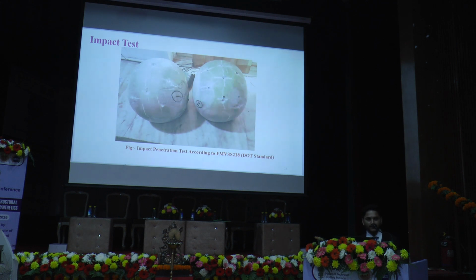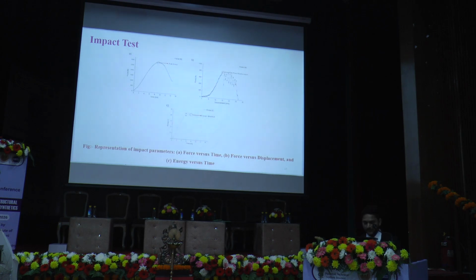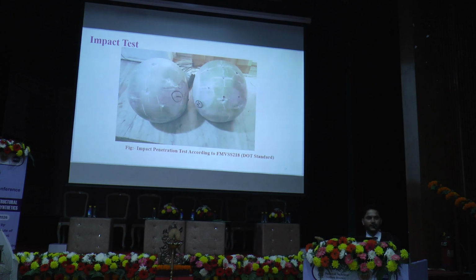In that standard, the striker penetrates the helmet shell from a 3 meter fall. So here we have to calculate the bulge zone after the peak acceleration, to check that after the liner the striker does not penetrate to the head skull, so that the bulge zone can be evaluated after the impact test.